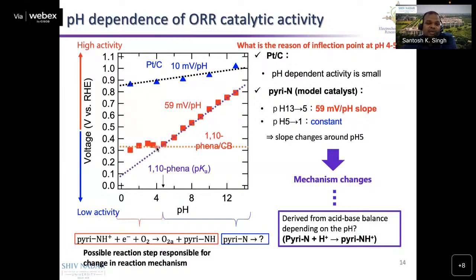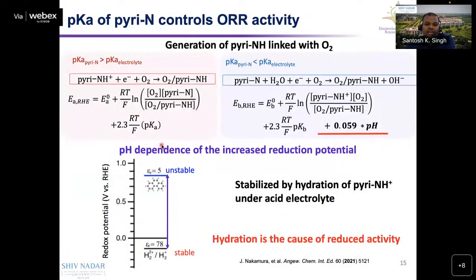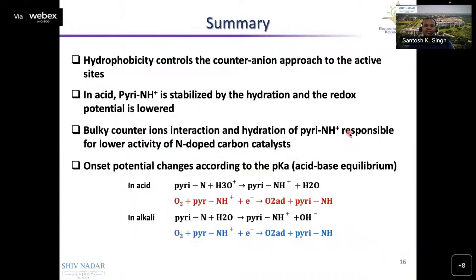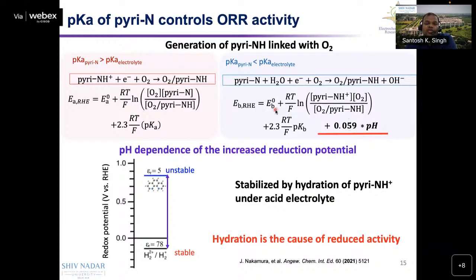So we anticipated that this deflection is because of the 1,10-phenanthroline pK value, which is responsible for the deflection point, and it always depends on the pK of the electrolyte. And we derived this equation, and we have tried to explain why there is a 59 millivolt change in the slope when we are talking about the acidic electrolyte, and when the pK of the electrolyte is higher than the pK of this catalyst. So these are the recent developments we have done in the case of nitrogen carbon catalyst.